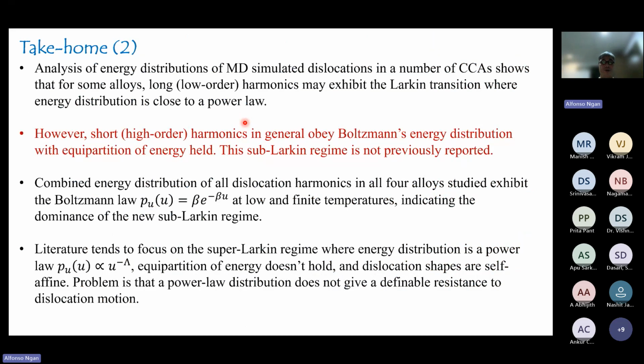So take home 2 would be that by analyzing the energy distributions of MD simulated dislocations in a number of CCAs, we found that the long harmonics may exhibit the Larkin transition, where the energy distribution is close to a power law. However, for short harmonics, we have a Boltzmann distribution, and the equipartition of energy also holds for the short harmonics.